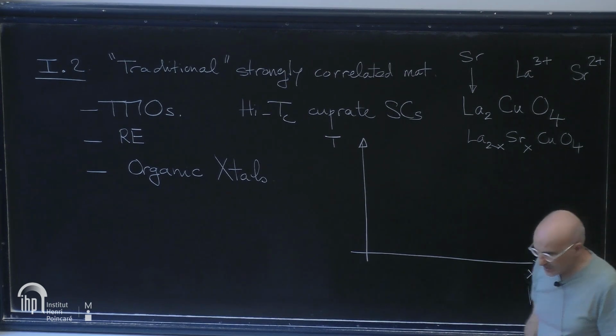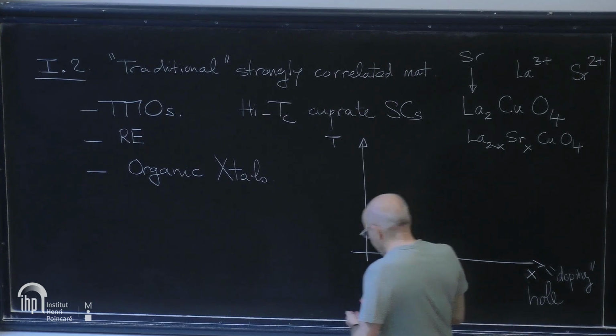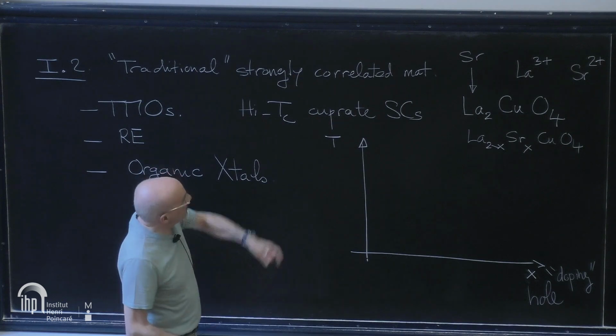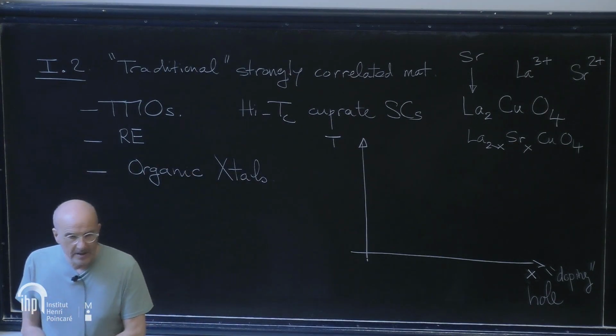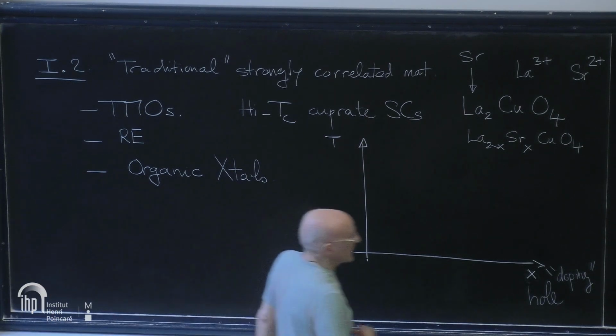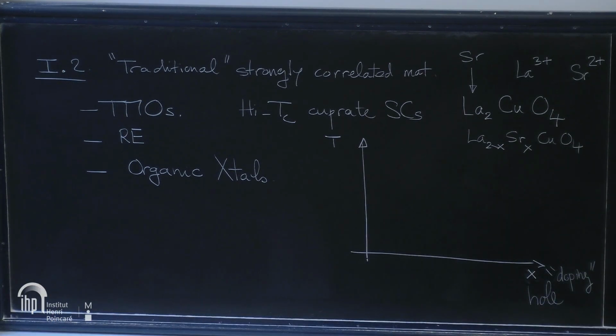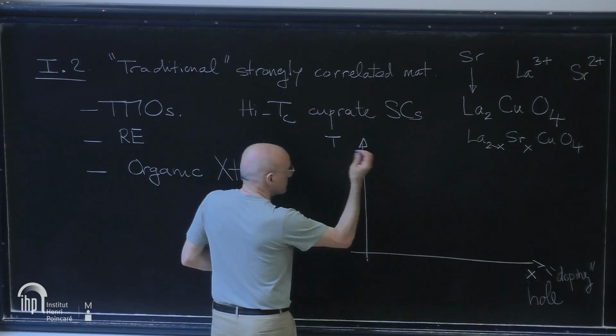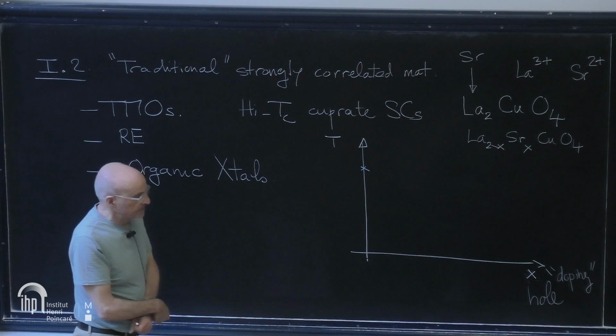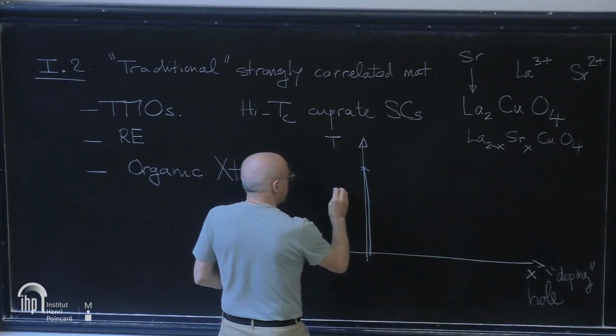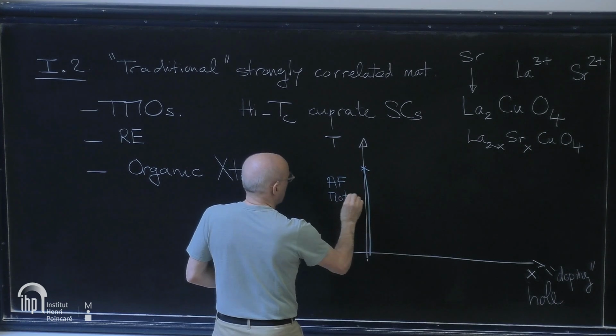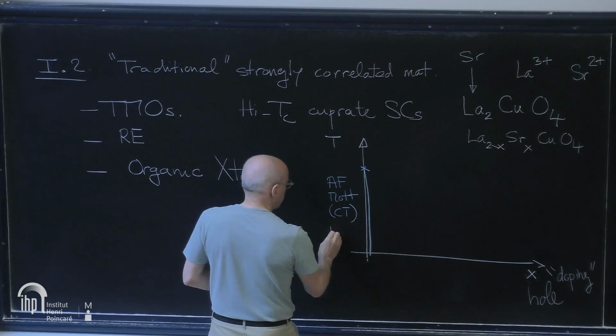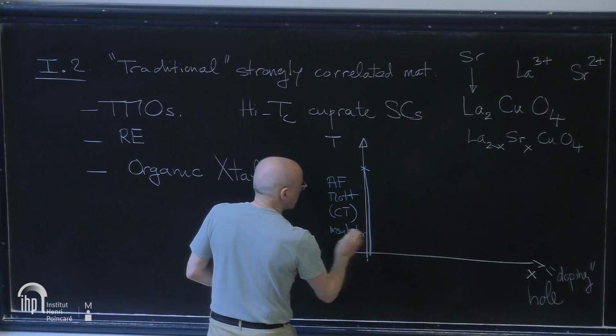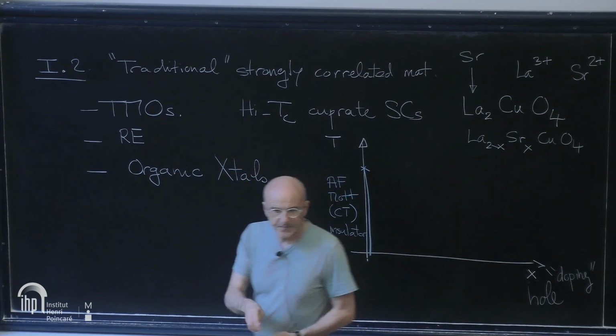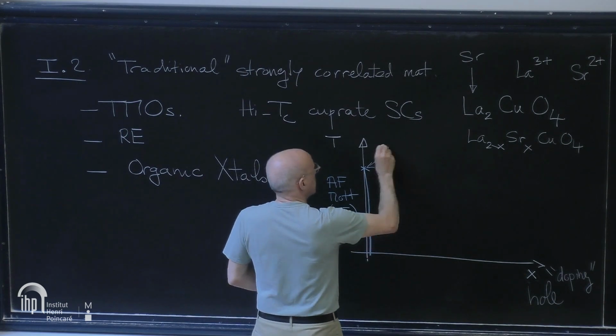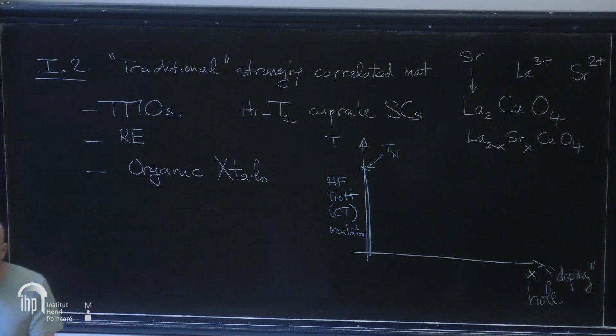And then very interesting things happen, which you've all heard about, I guess. First of all, when the system has no doping, this material is one of these Mott insulators, which is an insulator despite the fact that it has a half-filled shell. And it's actually an insulator which at low enough temperature becomes ordered. So there is an ordered antiferromagnetic phase here, an antiferromagnetic Mott, or actually more properly designated charge transfer insulator. Charge transfer because U is really the charge transfer energy. And this Néel temperature here can be high. It's typically several hundred Kelvin, let's say 400 Kelvin.